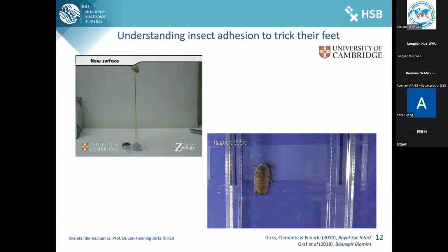At the same time, a project I did together with Stas Gorb, many of you probably know him here, at Kiel. So we also looked at this critical roughness. So insect adhesive systems, they are good at sticking to smooth surfaces, to glass, for example, because they have this adhesive liquid, we call it that, and they can make capillary adhesion together with friction. But they also have their claws. The claws play an important role to attach to certain surfaces, so if they are rough, for example. And what is nice, there's basically a kind of Achilles heel. So there's a very dangerous roughness for an insect. If it's very rough, they can use their claws. If it's very smooth, they use their adhesive pads, and they can make close contact.